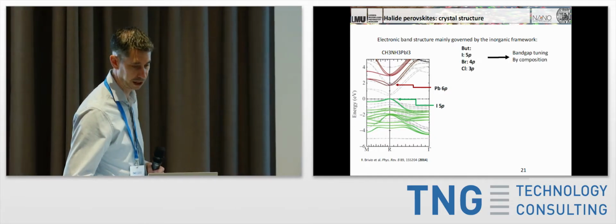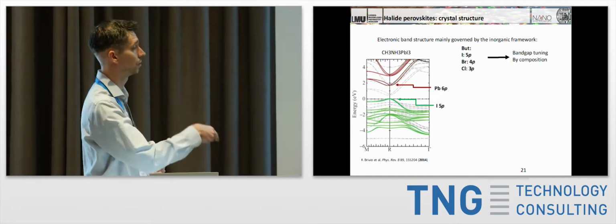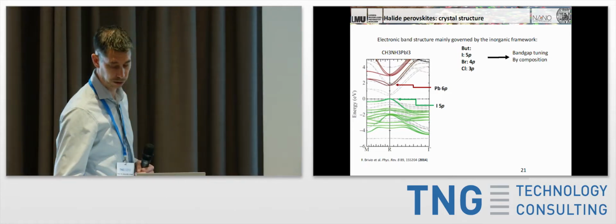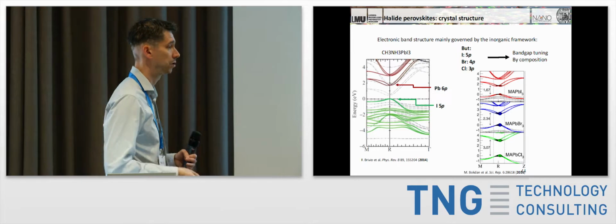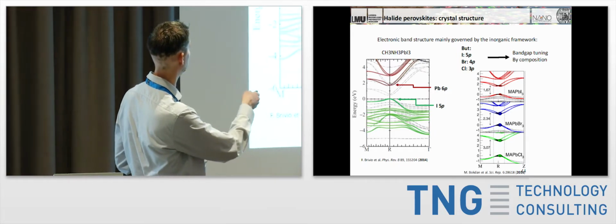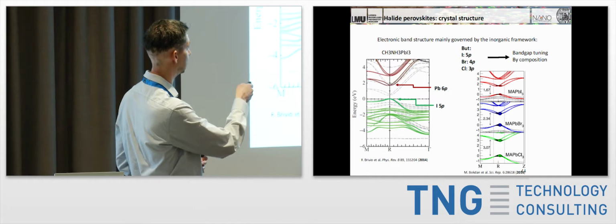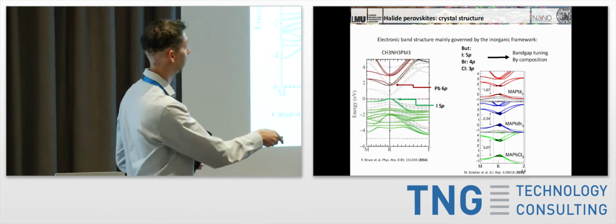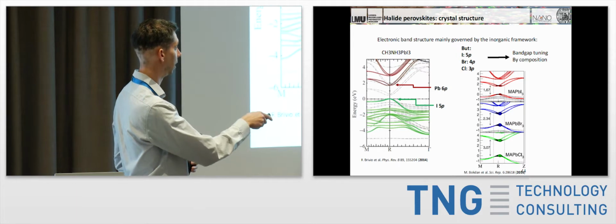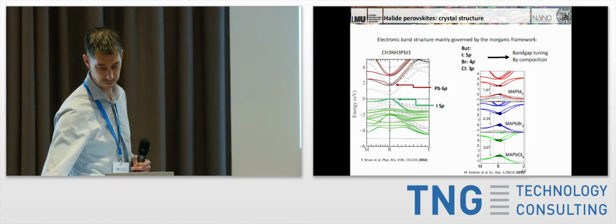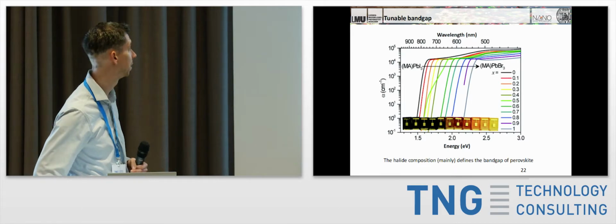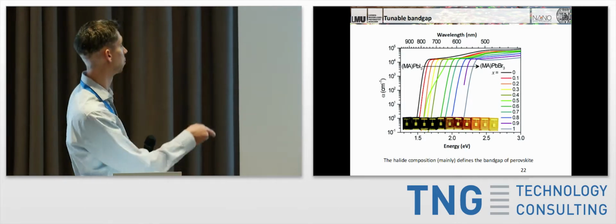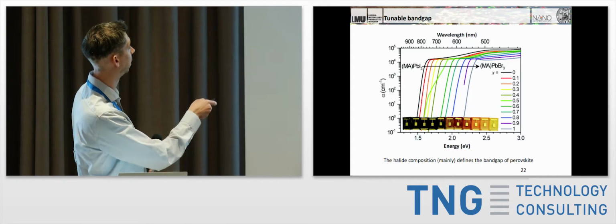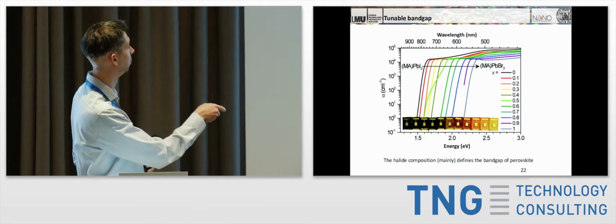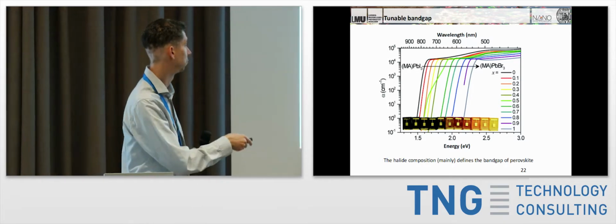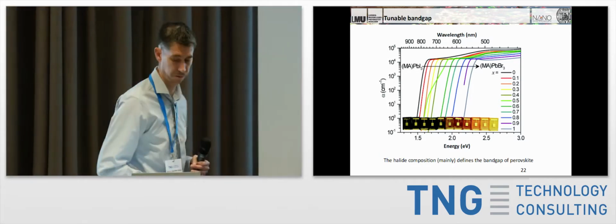And what makes the perovskites really interesting is that if you exchange the halides, which are in different rows in the periodic table, you can get a very efficient bandgap tuning just by tuning the composition. So essentially what you're doing is shifting the position of the valence band with respect to the conduction band, and so you're able to tune your bandgap from somewhere in the NIR out to nearly the ultraviolet range. And so now if you're looking at actual solar cells and the absorption spectra of these, varying the composition from purely iodide to purely bromide, you can see a very nice tuning capability throughout a very, very large range of the perovskite.